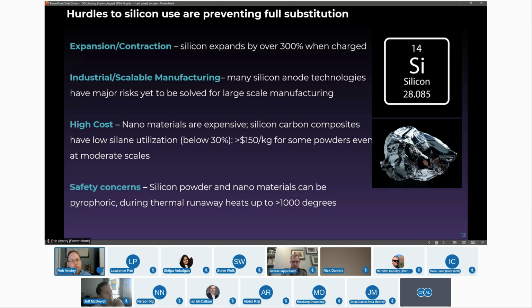And most of these powder-based processes get below 30% utilization from gas to active material in the anode, because you lose yield when you make the powders. Some of it goes in the exhaust, some of it makes powder agglomerations. You need to sift that out. Then you lose some during mixing, during coating, during calendaring, and then during the final cell making. So really the major issue is going to be how much silane actually makes it in the cell, and that's going to sort of be the lowest price you can ever go.